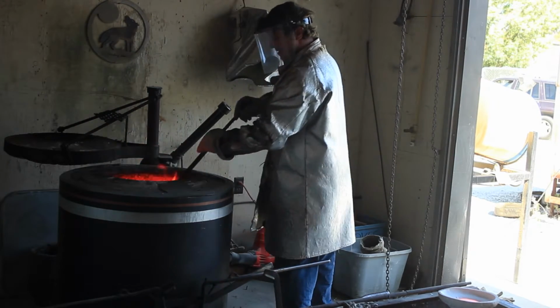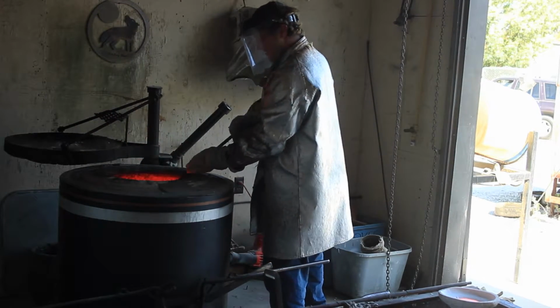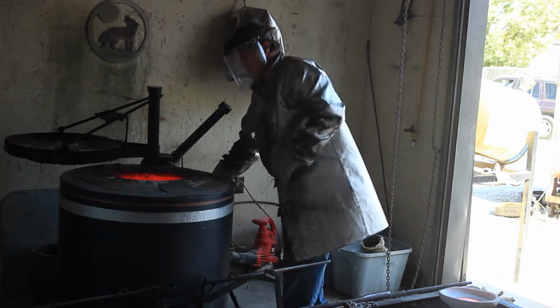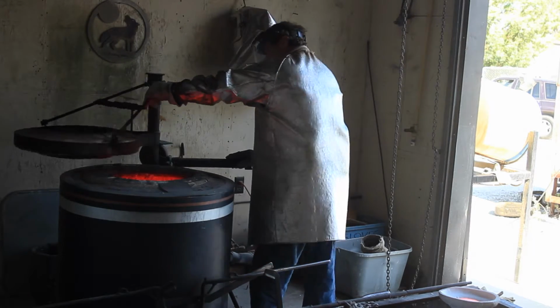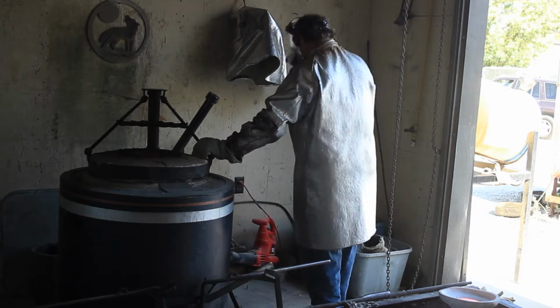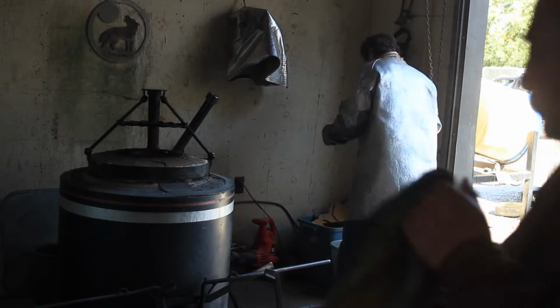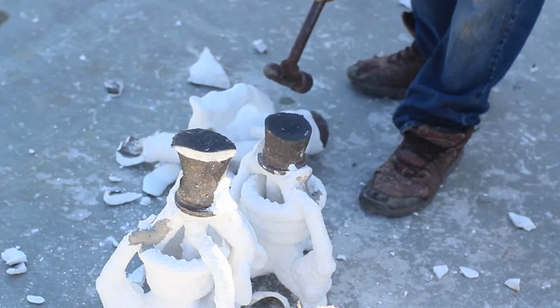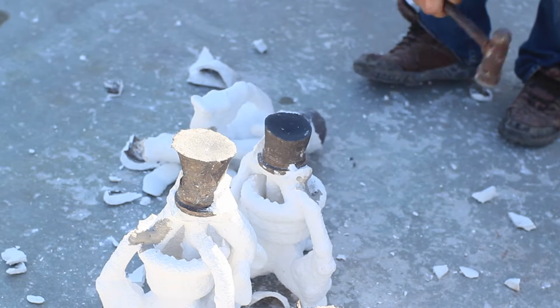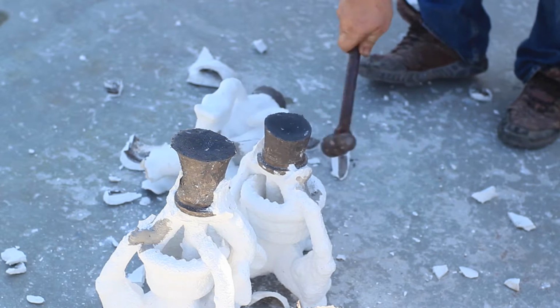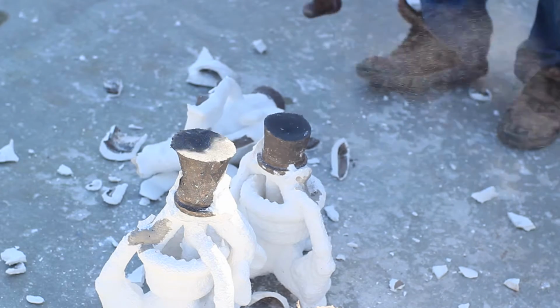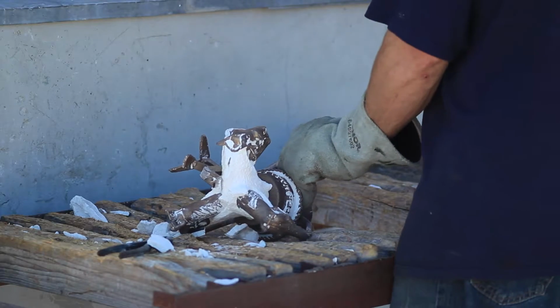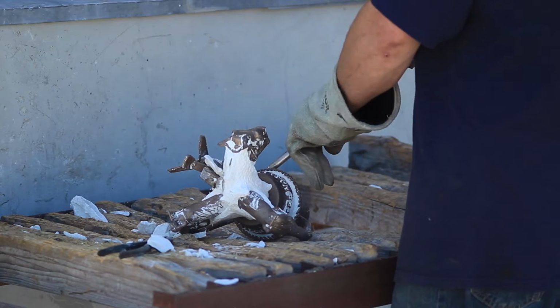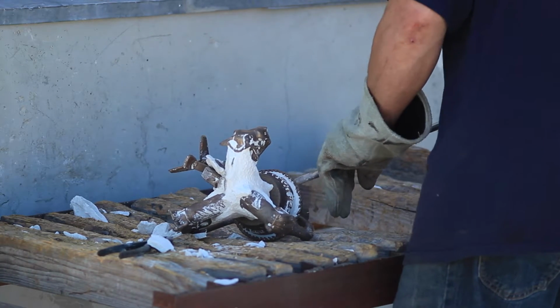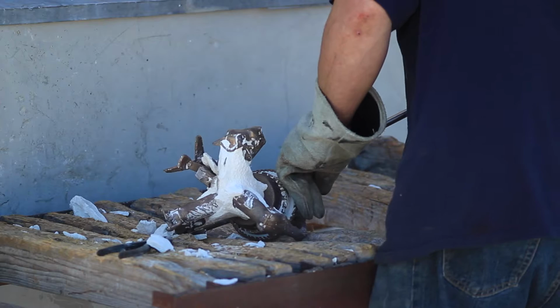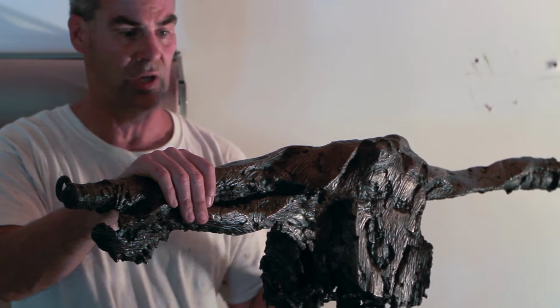Eventually, the bronze solidifies, and you break the slurry. Then you have your bronze piece. Once you break that slurry apart, you then go to metal chasing. That process is to get rid of all the chips and the impurities that sometimes creep in with the slurry, and you'll see slurry in the bronze, as well as you now need to weld pieces together.